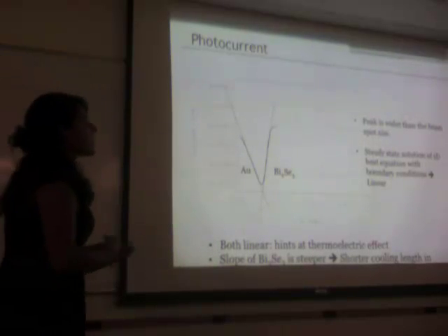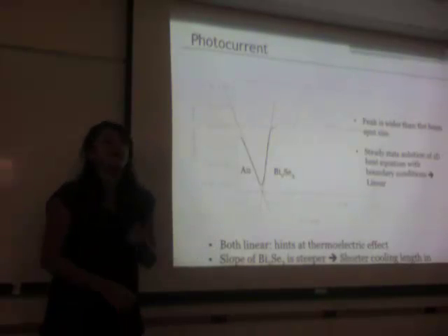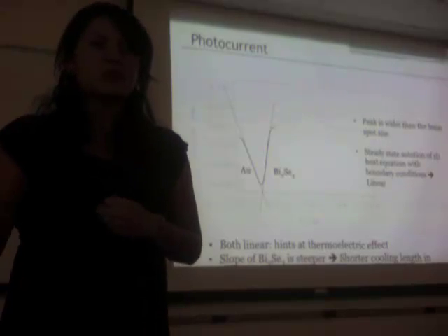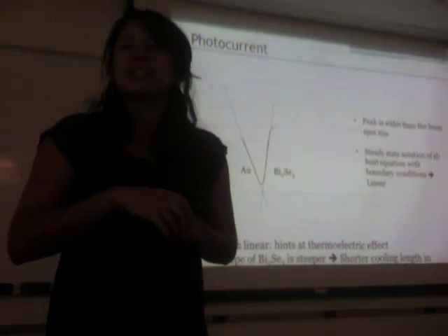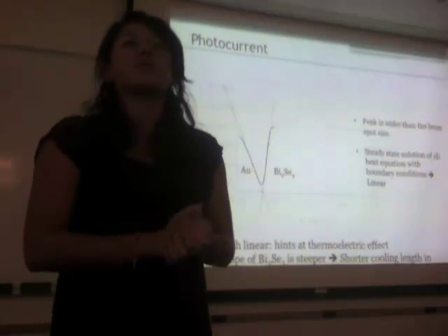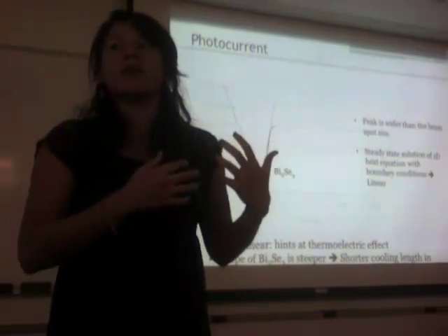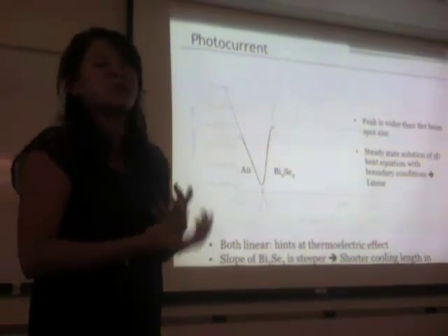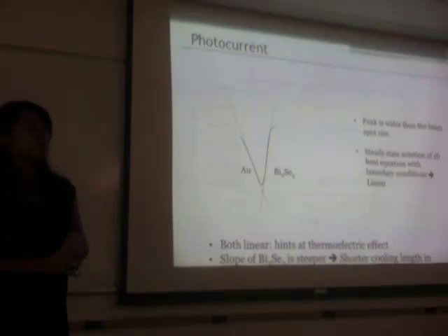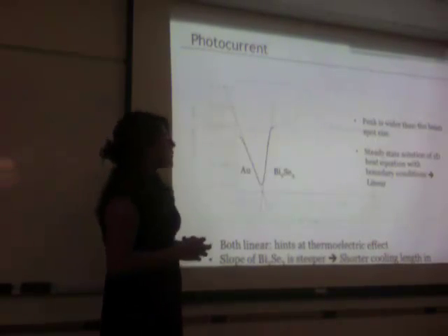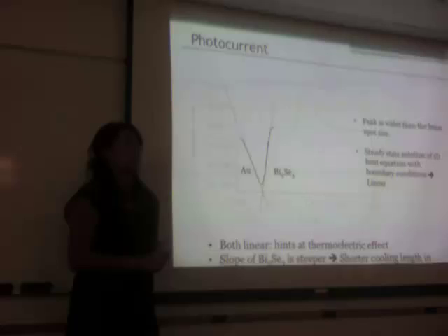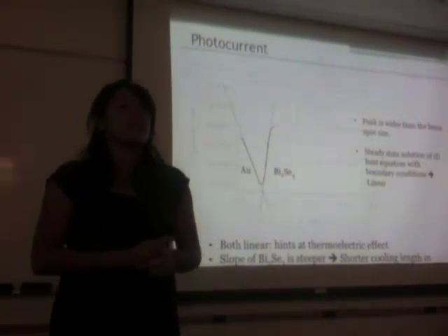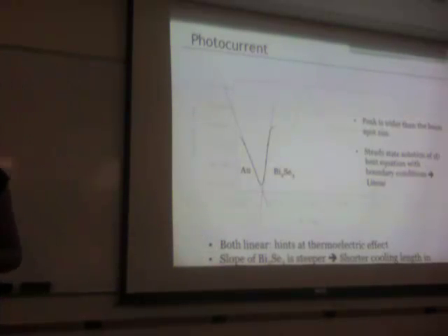However, this is data that we got from about half of our samples. The other half didn't work. Like I said, to make sure that the samples were okay, we tried to replicate the exact same measurements that they had done a year before when they were brand new. And we didn't get the same numbers. So I wouldn't trust the other measurements too much, and I'm suspicious of this. I wouldn't say it's conclusive evidence for the photothermoelectric effect in bismuth selenide. I would say it's preliminary.